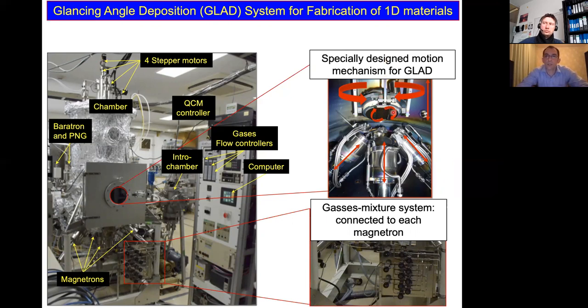Actually, we can rotate the substrate in both directions, and we can also change the position of the substrate as well as the distance. These are the magnetrons, which are located here, 4 pieces. And the gas mixture system is connected to each magnetron. Actually, we can work with 3 gases, which are usually argon, nitrogen, and oxygen.